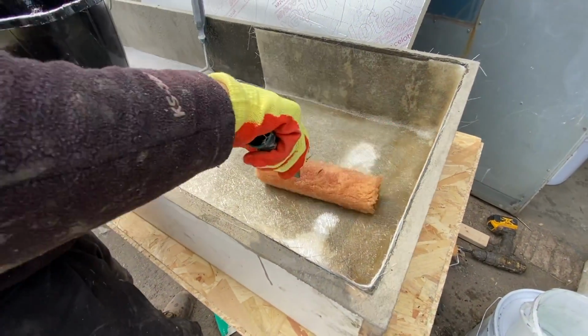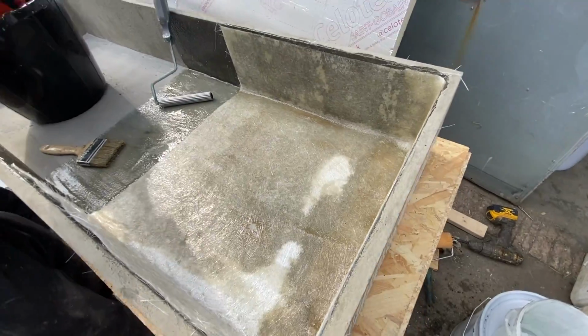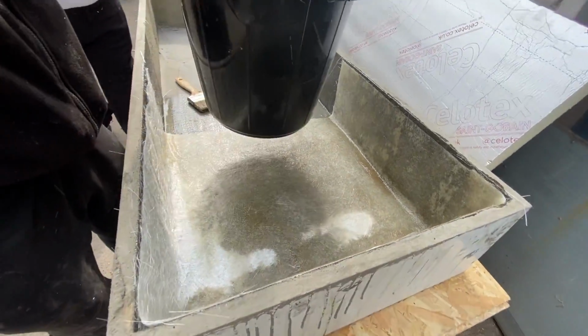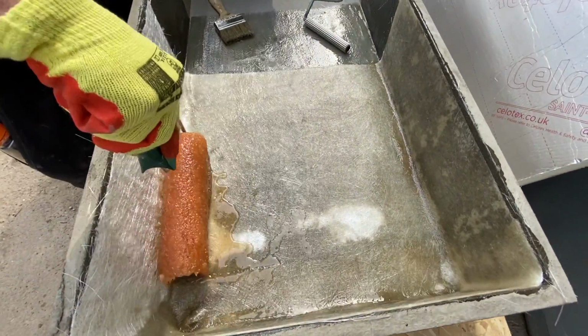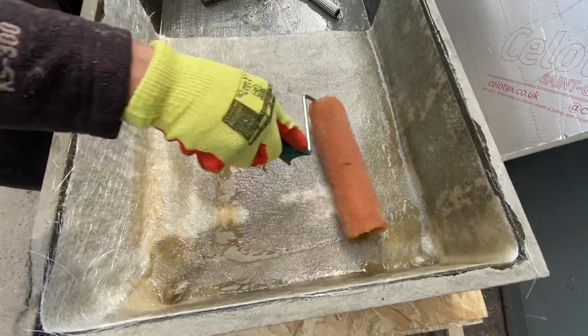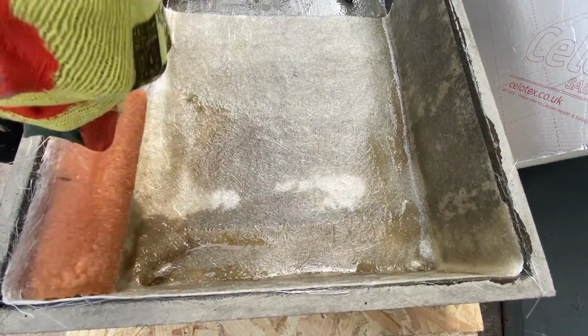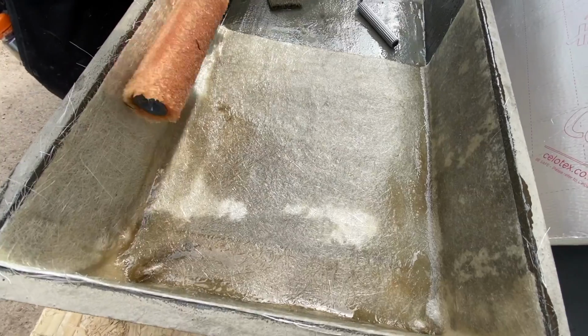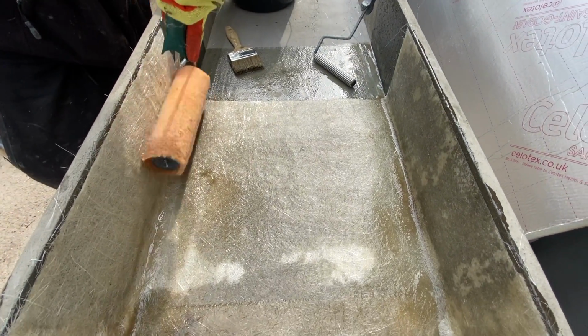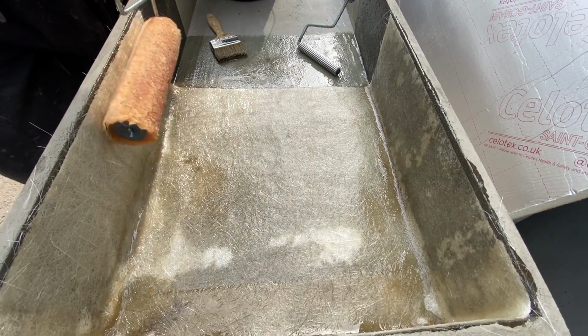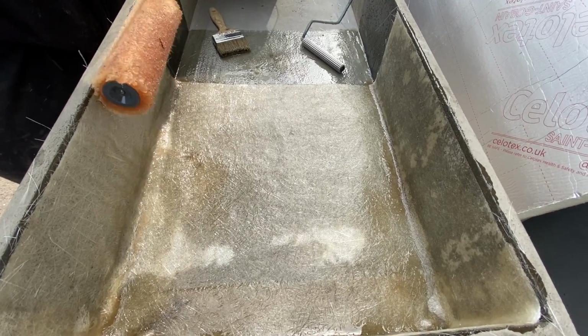You can see the air bubbles in this clip in the white, patchy areas. This is a sign that extra resin is needed, and extra pressure to drive them out. It's important to remove these because they'll introduce structural defects in the laminate and limit the lifetime.